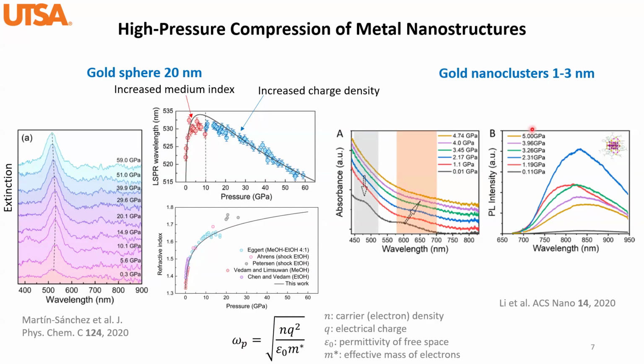On the right side, we have another group working on gold nanoclusters that are 1 to 3 nanometers. In this case, it's not localized surface plasmons, nothing related to plasmons, but at this size, gold clusters work similarly to a dye molecule. They emit light. The authors first saw increased photoluminescence intensity, and then above 2.3 gigapascals, they start to see a decrease of the photoluminescence intensity.